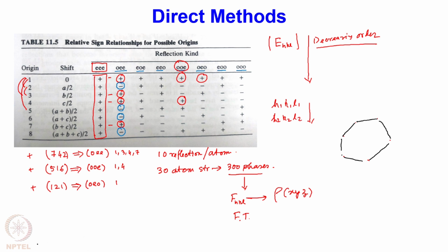And then we take that as a starting model and continue the process of guessing phases to completely solve the structure. So once we have correctly guessed a molecule, or part of a molecule, maybe like a benzene ring or whatever, these are used as known locations of the atoms. So now the rho x, y, z is known.